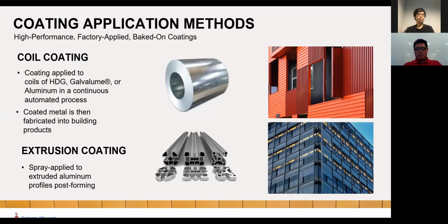And that's an easy way to remember coil coating: you coat it, then create it. Extrusion coating is spray applied to extruded aluminum profiles and is post-forming, okay? So for extrusion coating it is the reverse: you create it, then coat it. That's the major difference between these two, coil coating and extrusion coating. But both are applied by approved applicators and require high temperatures to cure.